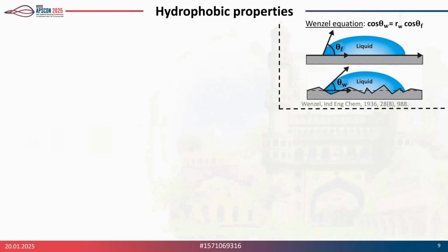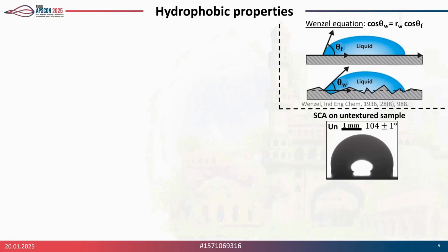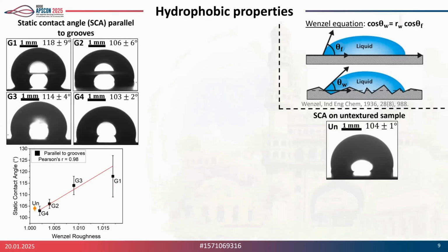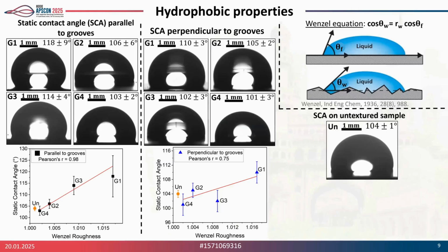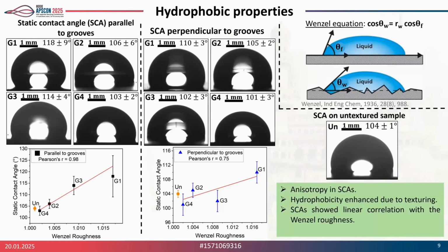All the prepared samples in the wetting were in the Wenzel state, wherein the droplet molecules penetrated inside the textures, and in such cases the contact angle can be given by the equation shown here, the Wenzel equation. For the untextured sample, the contact angle was 104 degrees, and for the textured ones, we measured parallel to the grooves and also perpendicular to the grooves. You can clearly see there is anisotropy in the contact angles parallel and perpendicular to the grooves. Also, if you compare with the untextured sample, the hydrophobicity got enhanced because of the texturing.